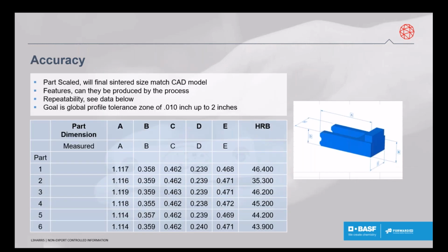We did a study on this part, and we wanted to learn some key aspects of printing and sintering for this type of geometry, and to see whether or not the features could be produced in the process. This chart below shows not only the fact that we can produce these features accurately, but what the repeatability was of the features after the part was sintered. You can see that the sizes are fairly consistent across all the dimensions that we measured. The parts were not printed at the same time, but they were sintered at the same time.